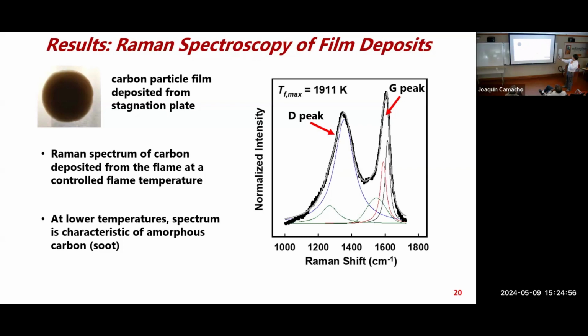If the flame is 1900 Kelvin, what we see is a Raman spectrum typical for soot formation. A lot of soot formation studies on Raman go into the intricacies of this. This is the D response of carbon to these Raman shifts, and this would be a perfect graphite peak. If there's only graphite crystal, you would only get this peak. This is some disorder or imperfection peak. And then there are these other amorphous features on which you can quantify a lot of the structure.